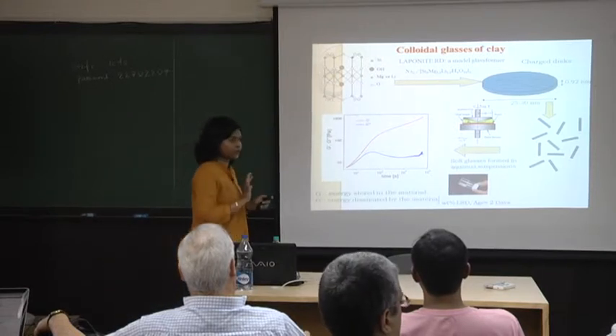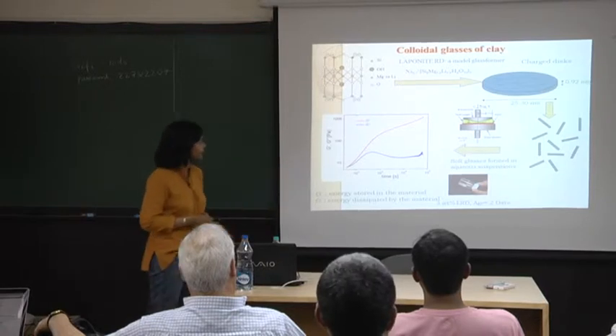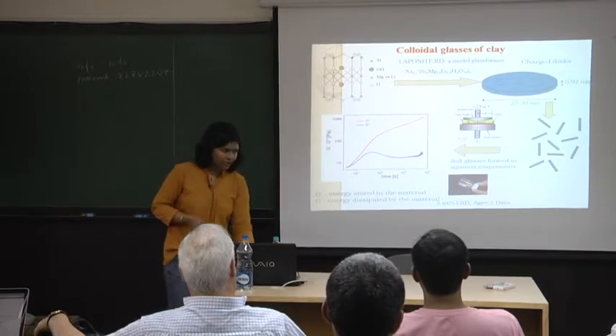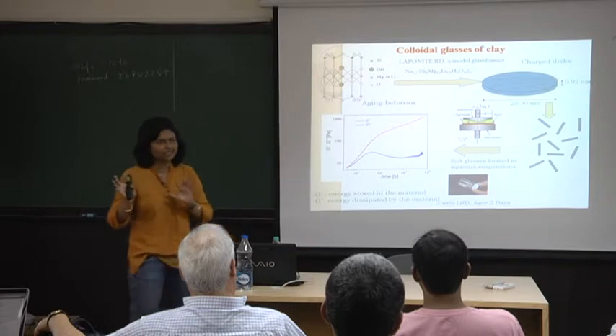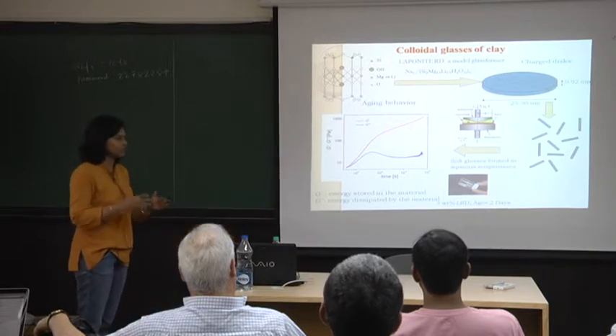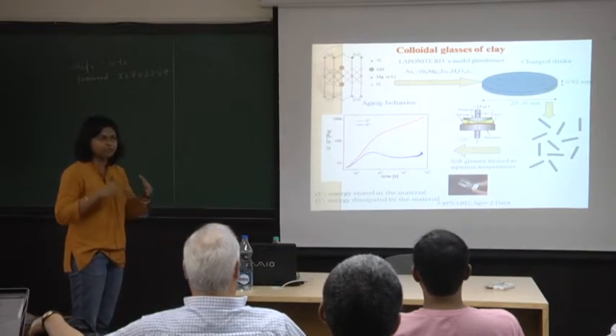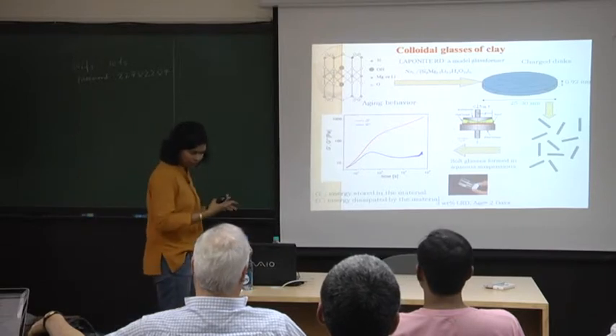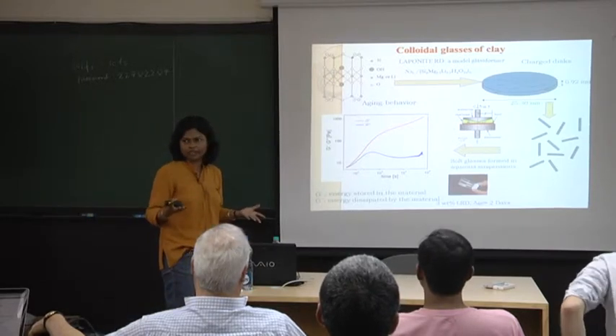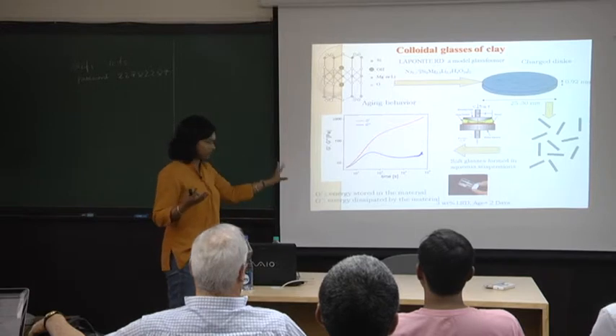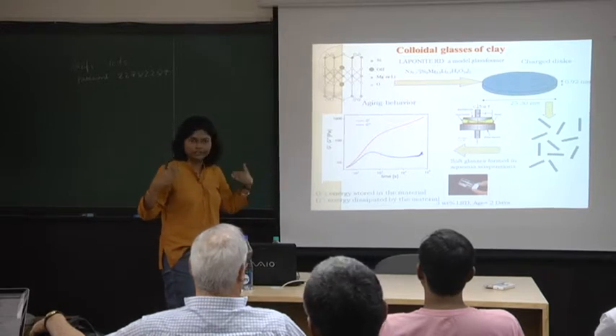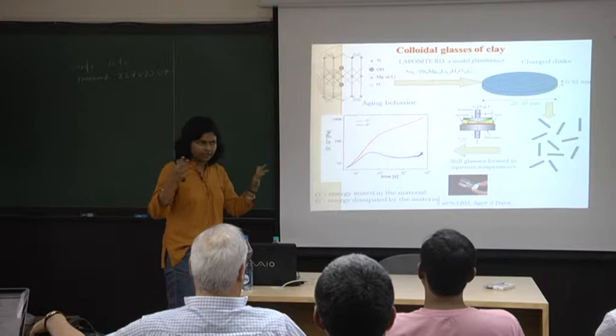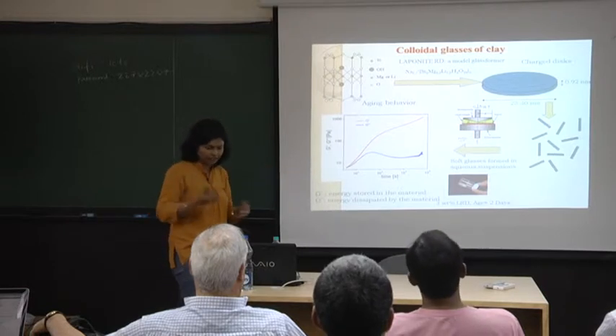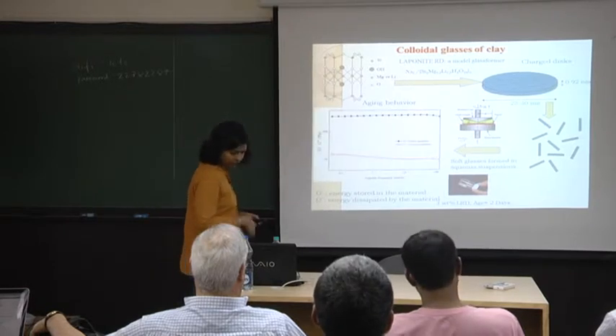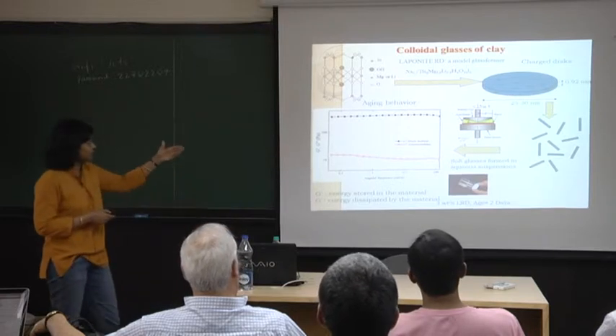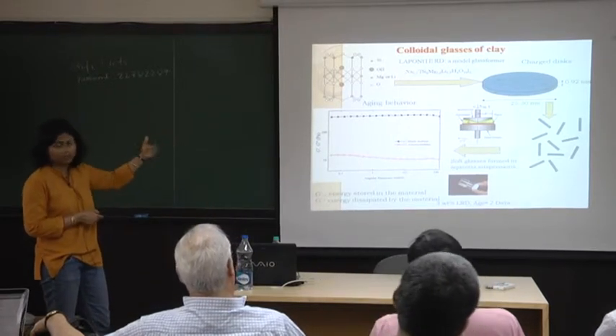This is at a very low frequency, as low as you can practically get. I keep calling it an aging behavior, but I should say that here the aging is not really the aging that you see in glasses below the glass transition temperature. The aging that I am seeing here is really an evolution of the dynamics in this particular material because of an evolution of certain physicochemical interactions that the particles share among themselves. There are other ways you can see that the material is starting to become solid-like.